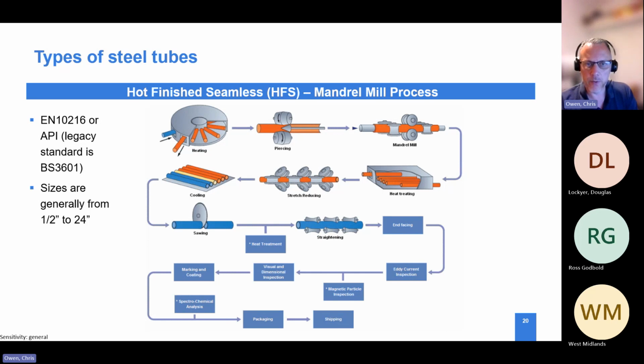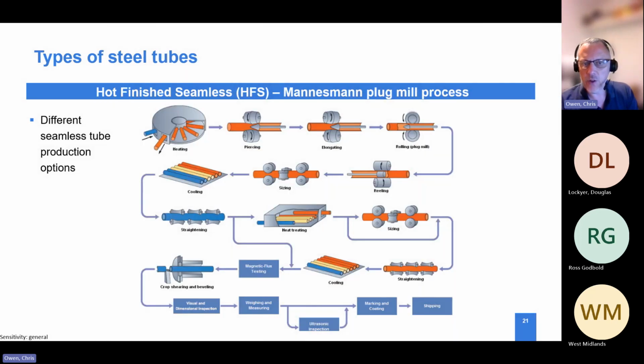So here's one example. And here's another example. They look very similar, but actually there are some differences in terms of how they process that tube once it's been initially extruded, stroke pierced. And again, one of the advantages seamless tube has, because it's extruded and stroke pierced, is that the microstructure is elongated as part of that drawing out process, which then means that tube is less likely to suffer from creep at higher temperatures compared to the coil-based manufacturing process.